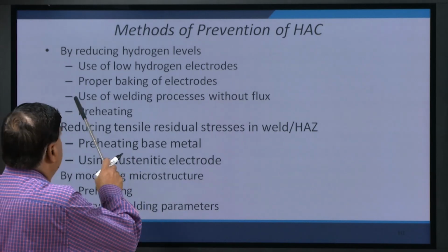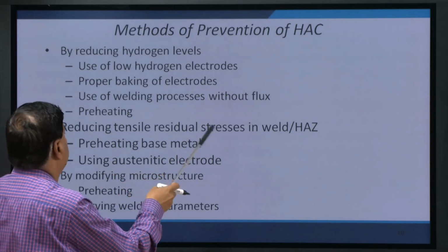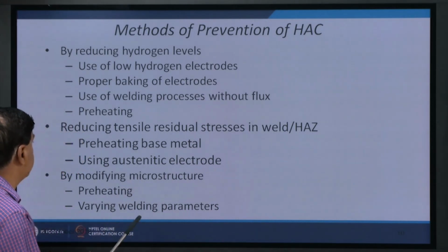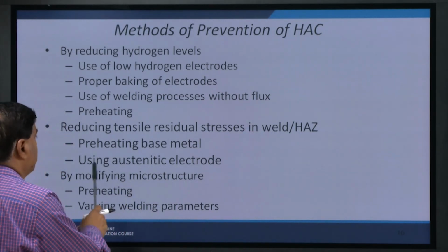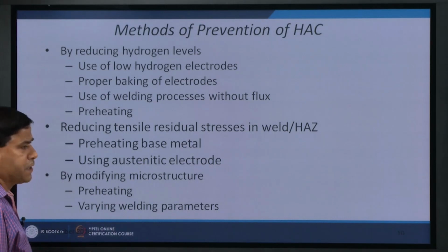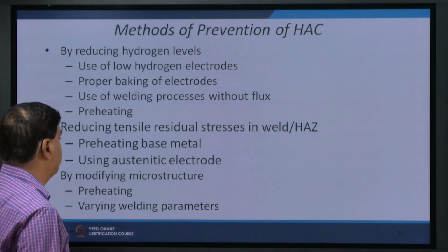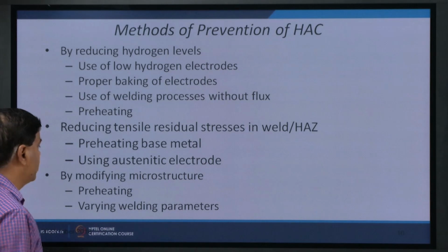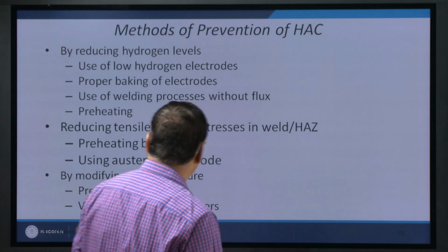These are the prevention methods, as I have explained earlier: reducing the hydrogen level using low hydrogen electrodes, proper baking of the electrodes, the use of welding processes which are without flux, or preheating. All these things I have already explained for reducing the hydrogen. Reducing the tensile residual stresses in the weld metal, as I have said, use of austenitic filler or preheating of the base metal also helps to reduce the magnitude of the stresses. And modifying the structure so that we have a less crack sensitive structure in the weld metal, like preheating, this helps